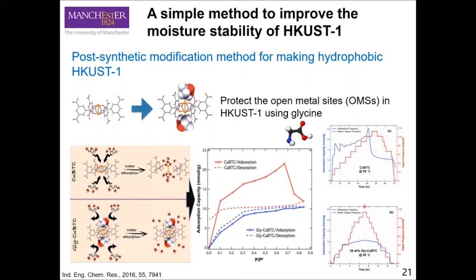As you can see, based on the water vapor absorption, after modification using this very simple method, we make the material hydrophobic. And the parent is still hydrophilic. So at high temperature, during the water vapor absorption, we have the collapse of the framework. But after modification, it becomes hydrophobic. And this is something quite interesting, but the method is very, very simple, and this is quite important for some potential practical uses. We also compared the CO2 absorption performance, which is quite comparable. So we were quite successful in developing this very simple method to turn the hydrophilic copper MOF into a hydrophobic copper MOF.